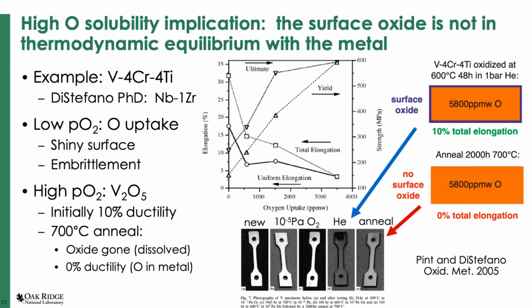So one more experiment that Jim and I did. I listened to him for many years talk about what he did on his PhD thesis on Nb-1Zr. And so I decided to repeat that experiment for some vanadium alloys that we were studying for the fusion program. And we're looking at how vanadium alloys would react in a helium environment, perhaps with some oxygen impurities. And so the interesting thing is, if you expose a vanadium alloy at say 600 degrees C into a low partial pressure of oxygen, you have oxygen uptake. The specimen comes out shiny. Here's an example down here. But if you pick up enough oxygen, you'll eventually embrittle the alloy.